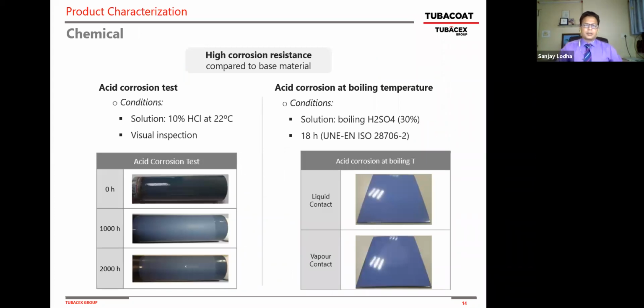This is just another example on the chemical properties. I took one example of hydrochloric acid and sulfuric acid over 2000 hours: 10% hydrochloric acid at 22 degrees and sulfuric acid at 30%, which is very corrosive. Using the European test in both conditions, again, this Tubacoat material holds very well. There are many, many more tests we've done with molten salt, sodium hydroxide, you name it, and this holds very well in most applications.